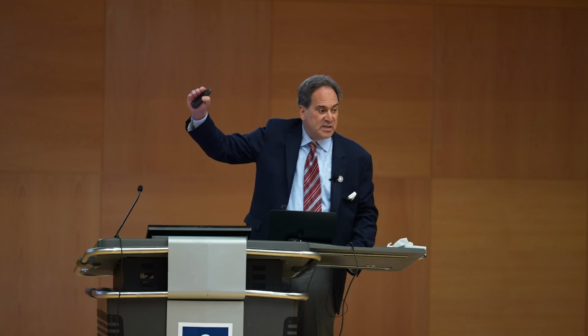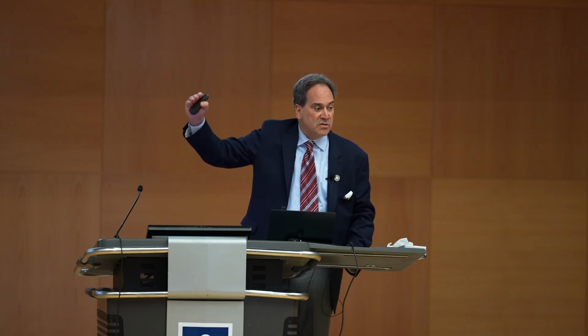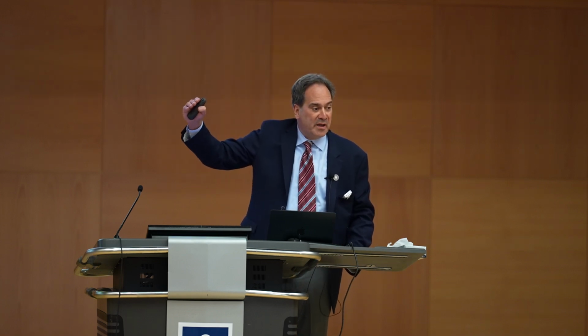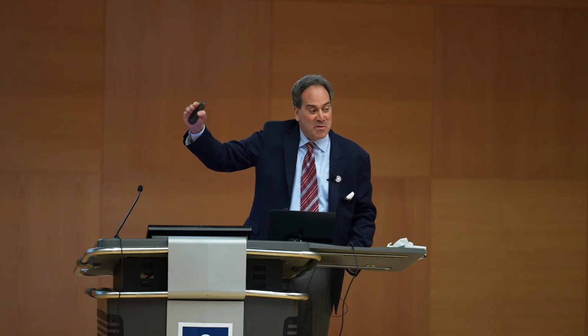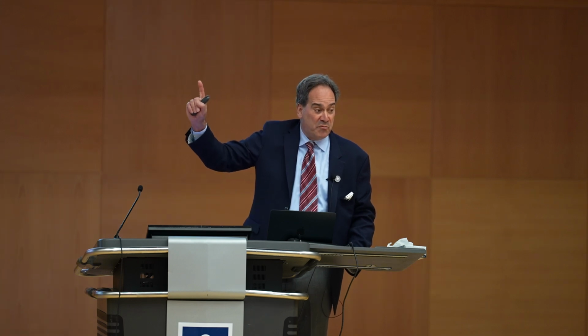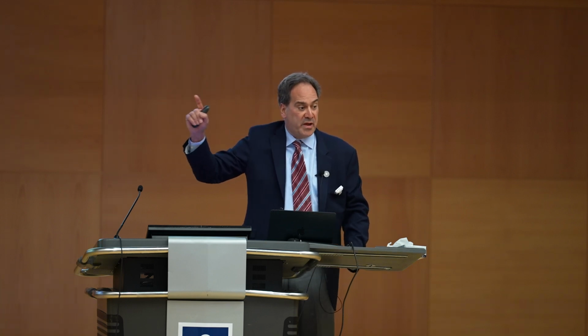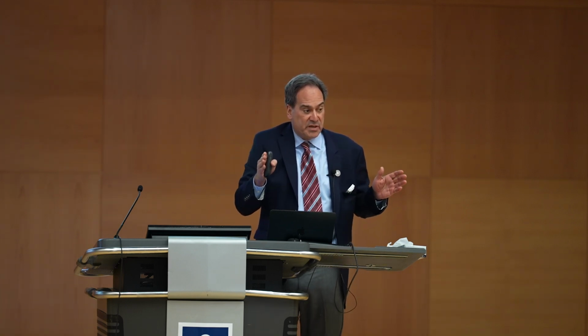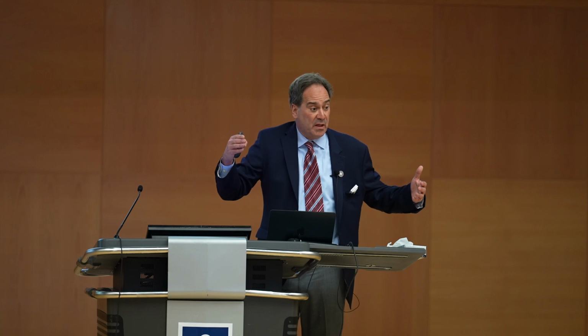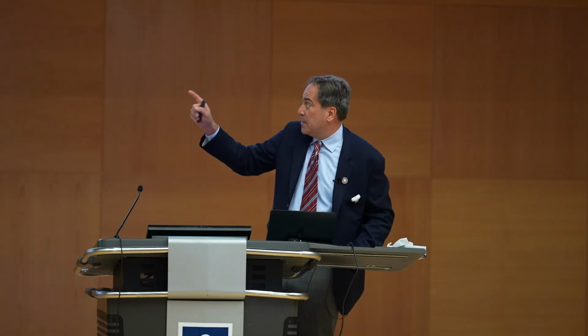And so I looked at the students, I said, great, we just blew $2 million trying to make a more complicated catalyst that's no better than platinum. And they said, no, you don't understand this. We made a catalyst that's as good as platinum that uses 1/7 the amount of platinum, and that was a world record at the time. And that is a win. That's an important thing where we're trying to begin to replace, our reliance on different types of elements. Really critical capability here.